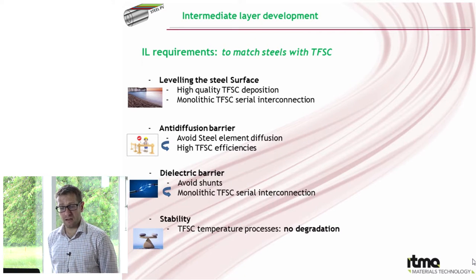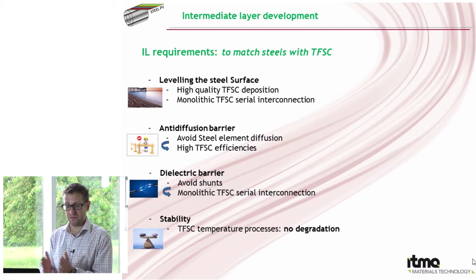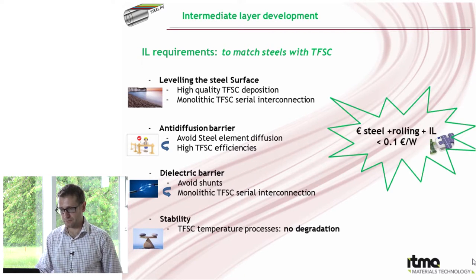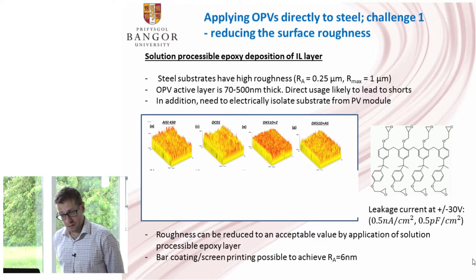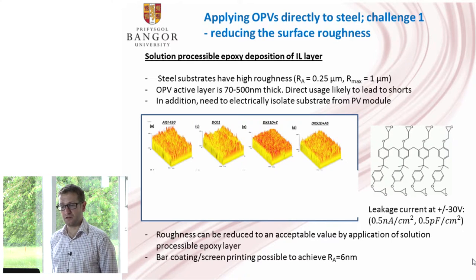But that intermediate layer also needs to avoid diffusion of elements from the steel substrate into our solar cell, and it also needs to act as a good dielectric barrier, so we can't have any voltage shorts between our steel substrate and our solar cell. So in Bangor, we've developed a process where we apply an epoxy-based coating onto steel. So typically the steel substrates have a relatively high initial surface roughness. Maybe the Ra of these substrates are about 0.5 microns, and Rmax can be anything from between 1 and 5 microns.